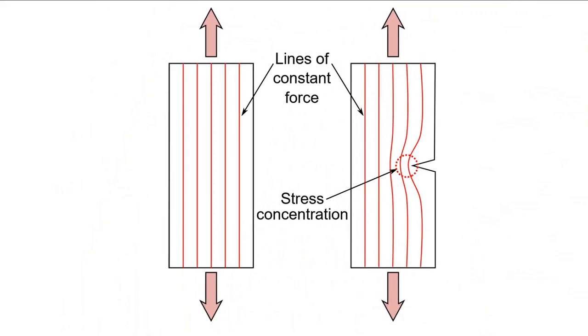Let's now examine how a load can change across a cross-section of a small portion of material. If the material is monolithic, that is, has a constant cross-section, then we can draw isolines of constant force across it. If there's a small flaw on the side of the material as depicted, then the isolines will have to bend and concentrate immediately approximate to the flaw. This means that the stress will appear locally much higher near this flaw. Let's now look at how this type of flaw can appear and how it relates to fatigue.